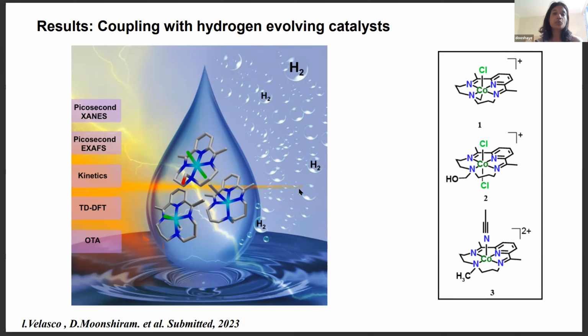In this case, we looked at three cobalt catalysts with hydroxymethylene, hydroxymethyl, and methylene amine substituents together with the ruthenium photosensitizer, and through time-resolved spectroscopy, we were able to determine a complete mechanistic pathway followed by these catalysts. But importantly, the influence of these amine substituents showed that it is very important to have hydrogen-containing amine groups at the pendant position of these complexes, because they helped in promoting hydrogen evolution and can act as H-H bond-forming relays.